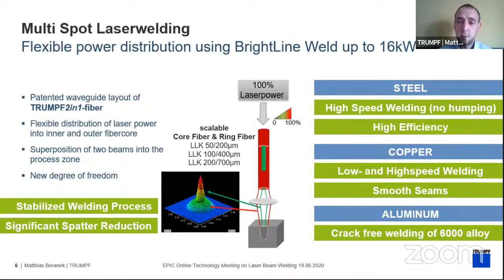In copper, we have the low and high speed ability, especially low-speed welding for higher penetrations. Not having a special fiber guide is difficult with copper. Now this has been overcome. And also we will see smooth weld seams, as copper is a little prone to blowouts and rough surface. So this is also improved.